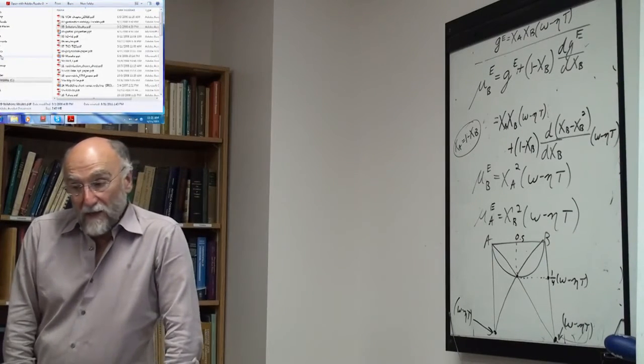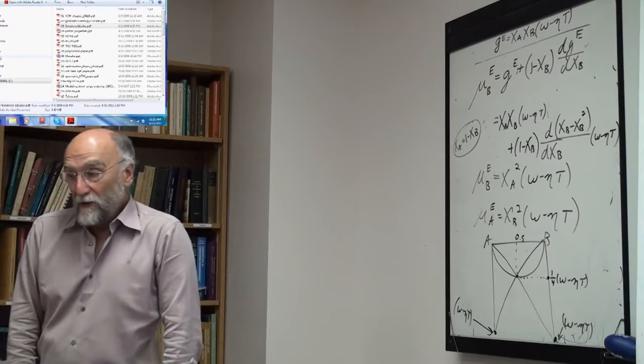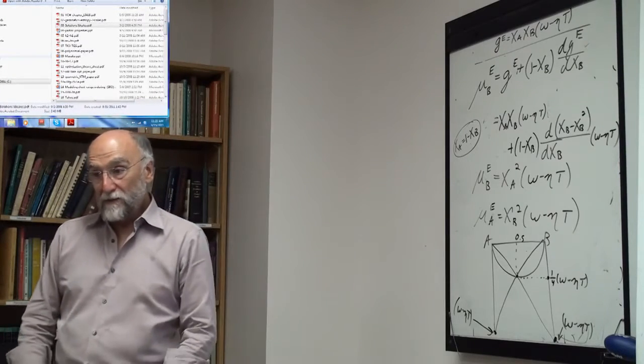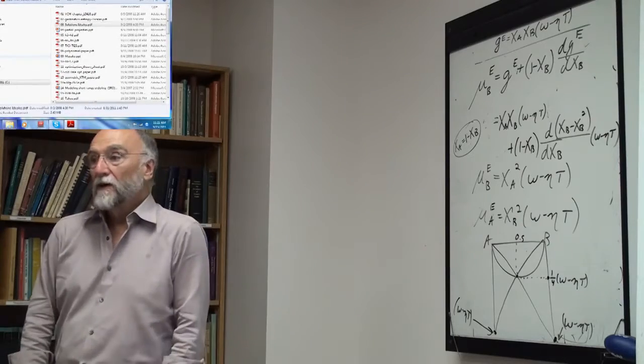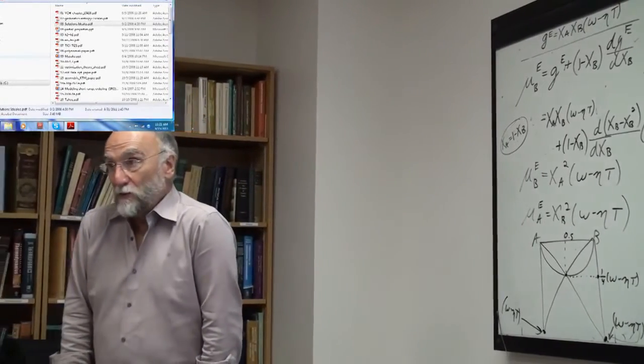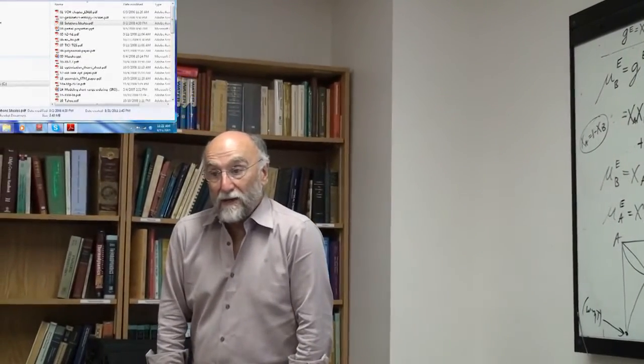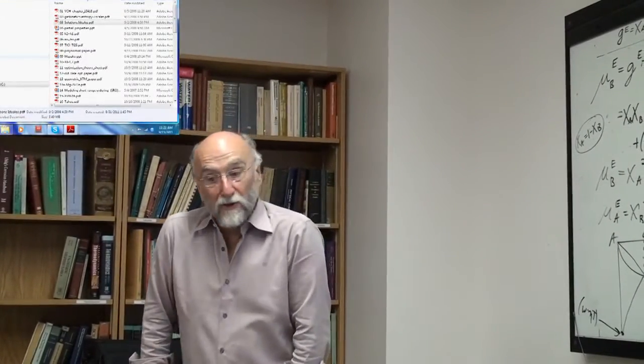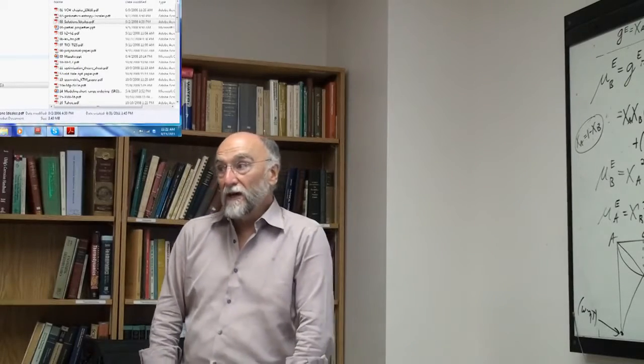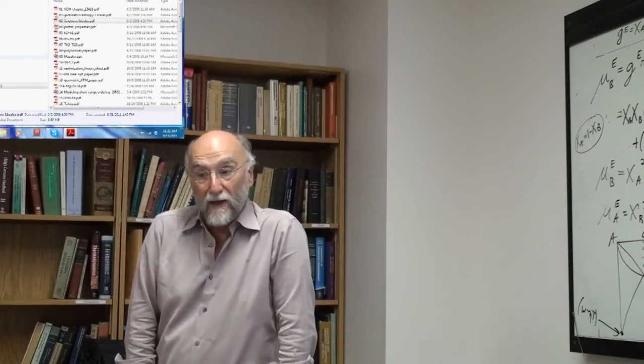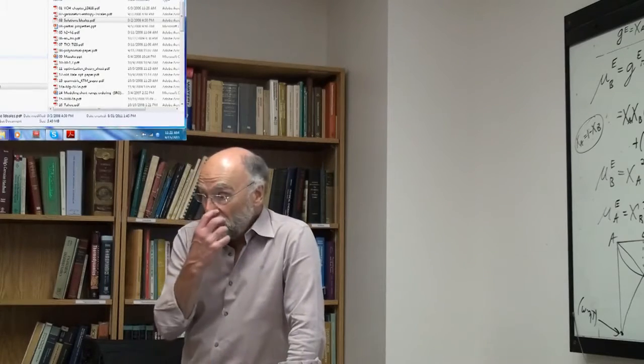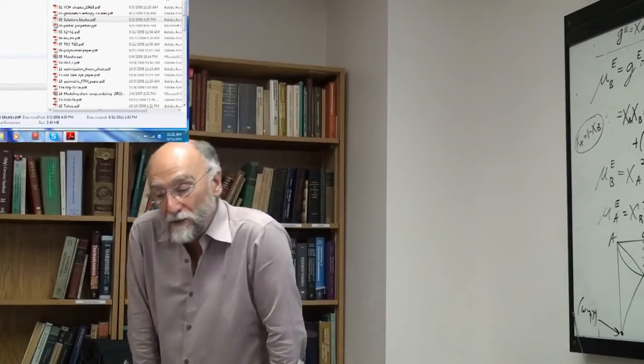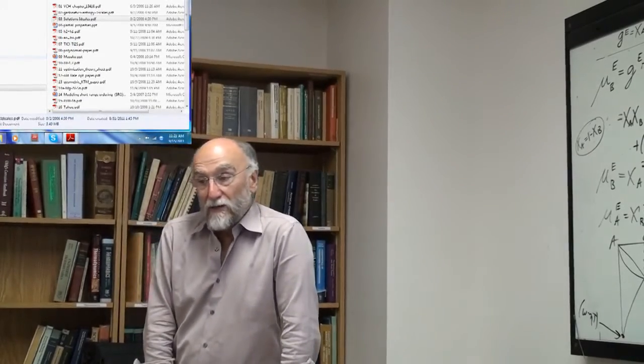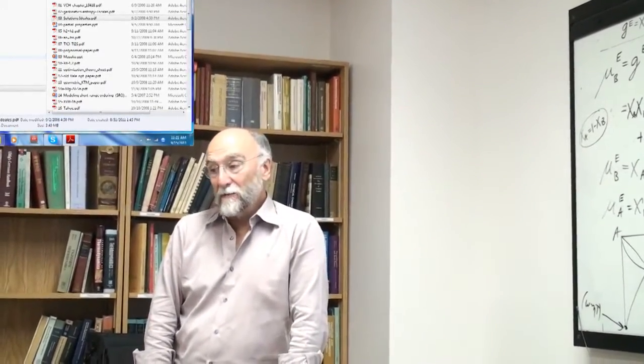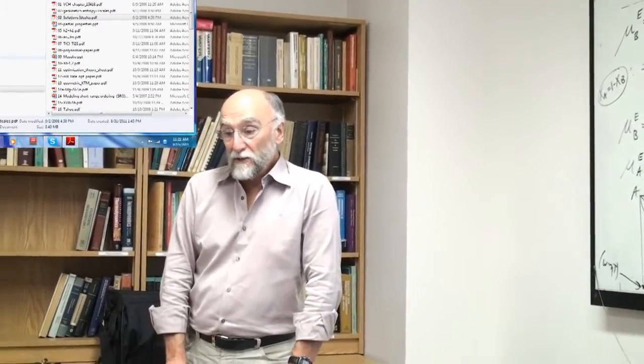Now, when we talked about ideal gases, I said that most gases, unless you go up to very high pressures, are very close to ideality. It's a very good assumption that the gases we're dealing with in material science are very close to ideal, with deviations of less than 0.1%. But with solutions, the deviations from ideality can be very large. You can have excess Gibbs energies which are several times the ideal Gibbs energy of mixing. The activity coefficient of an ideal solution is 1, but real solutions can easily have activity coefficients of 10 to the minus 2, 10 to the minus 8. You can have immense deviations from ideal behavior. So an ideal solution is just a limiting case.